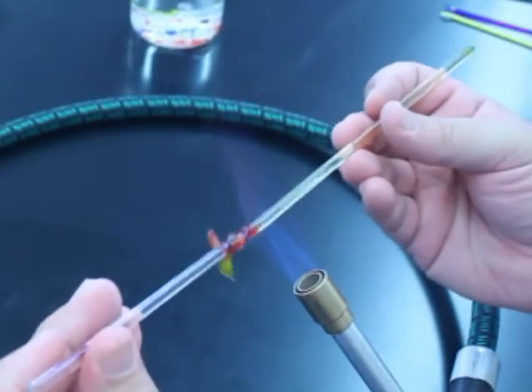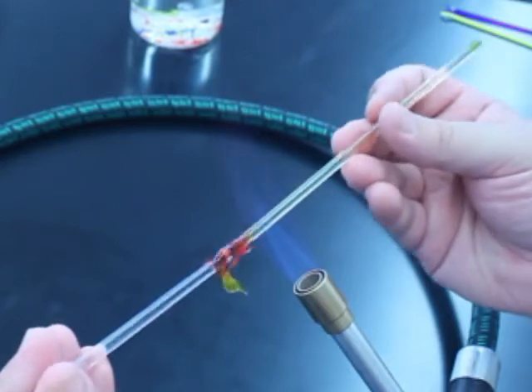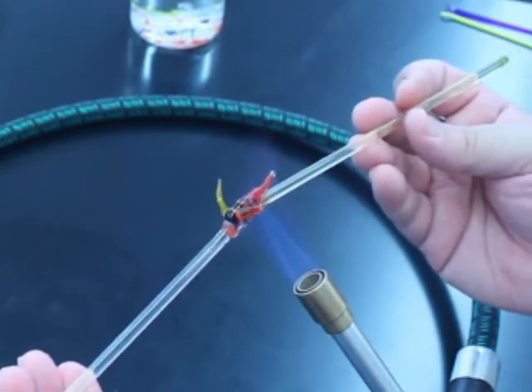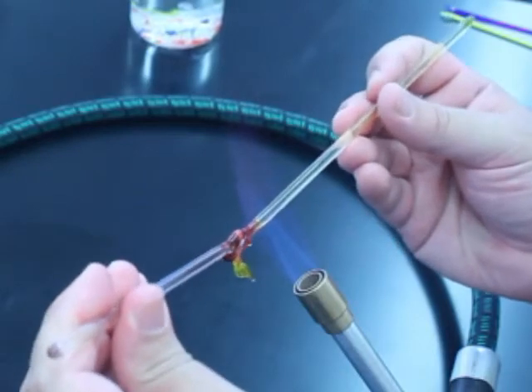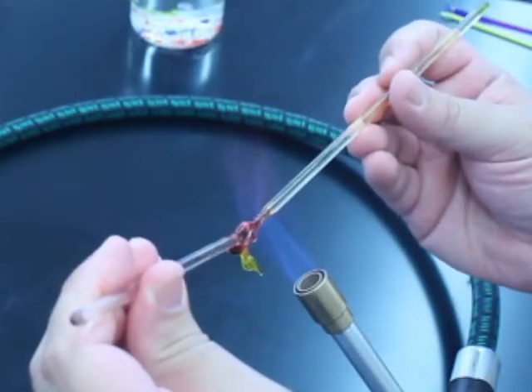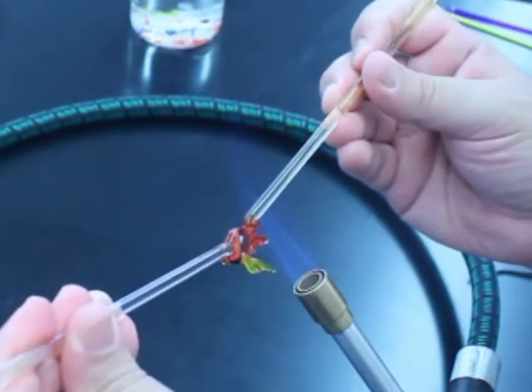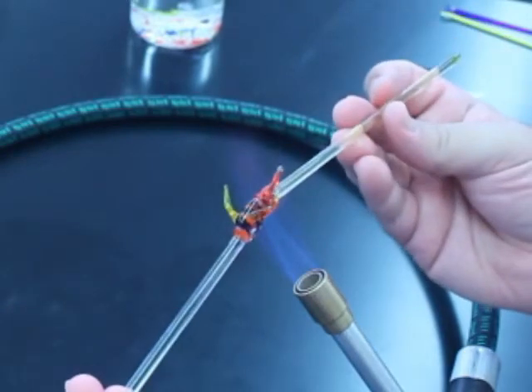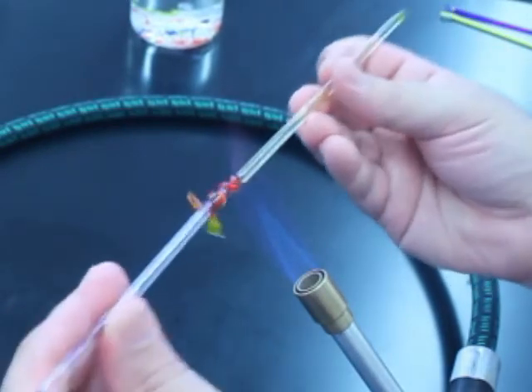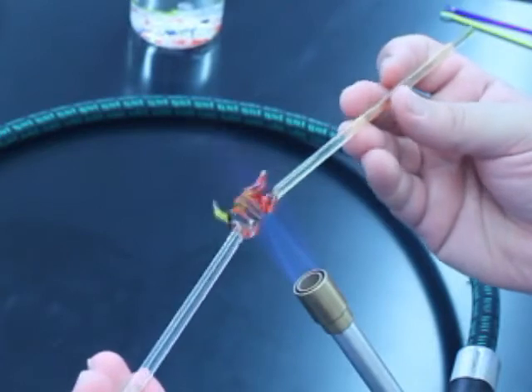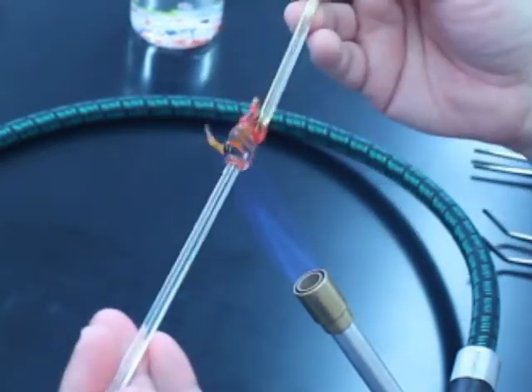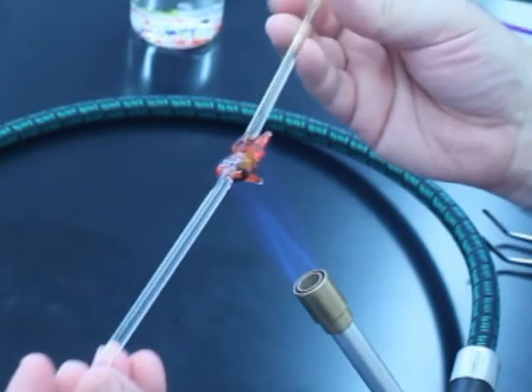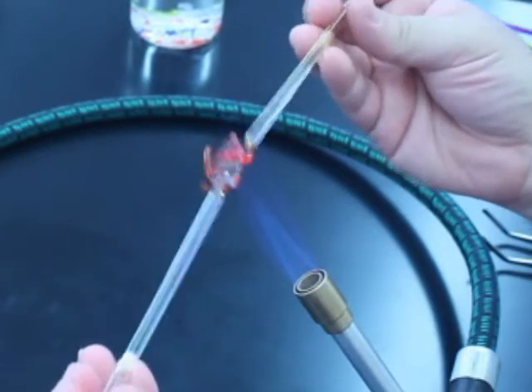if you notice how this rod is changing colors on me as it's working, you can see it's gone back to that yellow. So you have these striking colors, colors that only start to manifest as the glass is heated. And as you're actually working the hot glass, the colors can be changing on you. And that's perfectly normal, so you don't really want to worry about that. What it does tell me, for example, is see the yellow right there tells me that's cooling down. So I can go ahead and just heat that whole area up.